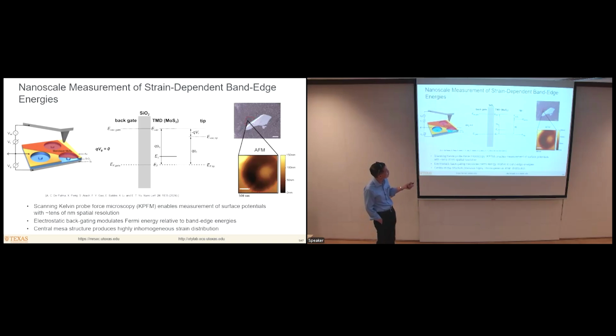What we have here in addition is this backgate contact. And what happens there is that if we apply, say, a positive bias voltage here, then that moves the energy levels down. And then there's a corresponding lowering of the energy levels in the sample, in this case, monolayer MoS2. But that decrease in the energies is affected by the fact that you can have carrier accumulation in the MoS2 layer. So it doesn't exactly track the backgate voltage that is applied.